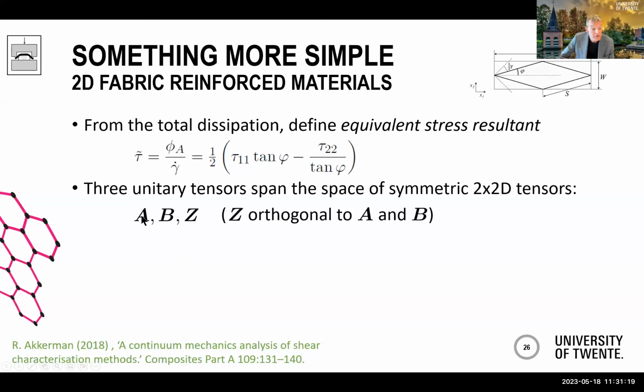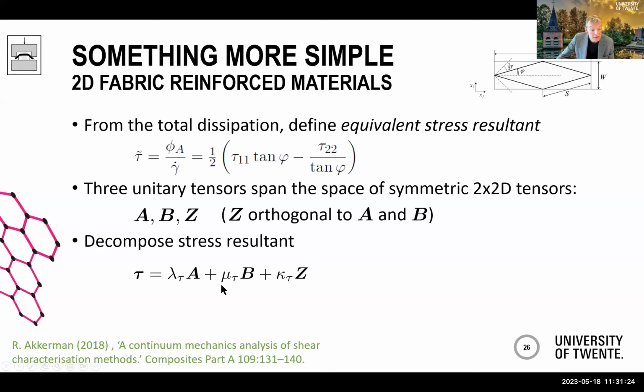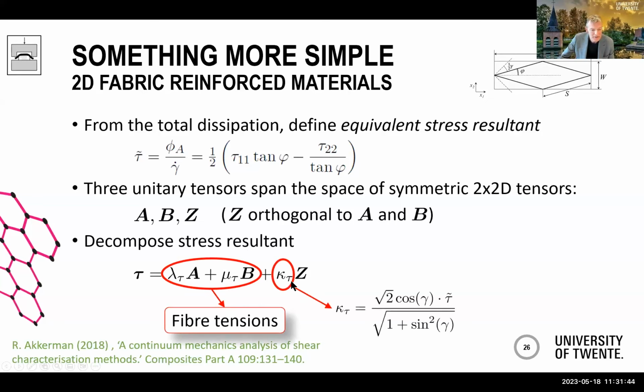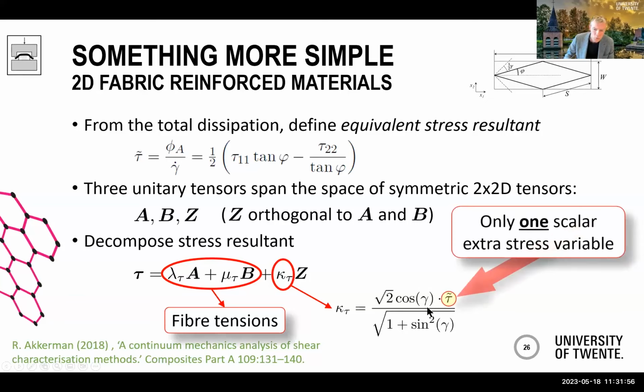Then you just need 3 tensors to span the space of this stress resultant. And the A and B tensor are nicely in the fiber direction. So these are fiber tensions, and only this in the Z direction is representing the actual material behavior. So we just got one scalar here, and we can formulate that scalar in terms of the shear angle and this equivalent stress resultant. So we just need to characterize only one scalar extra stress variable.